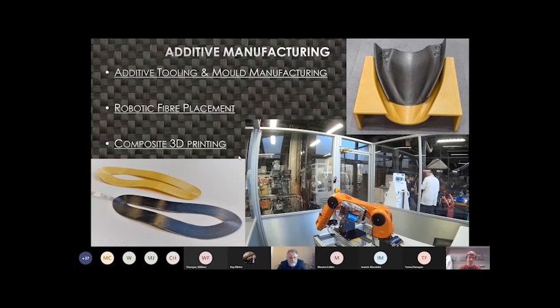So as William from NUIG said earlier, the Markforged system we would have used for the last 5 or 6 years. And this was used in conjunction with NUIG and ICOMP to print these carbon fiber insoles. And at the back there, you can see this lead coming out of the carbon fiber. Essentially that was a force sensor that was embedded into the part as it was printed. We were able to put these onto a person, and as they walked, it recorded data from the stresses applied to that point in the composite. So there's a lot of different ranges of application for this kind of technology.